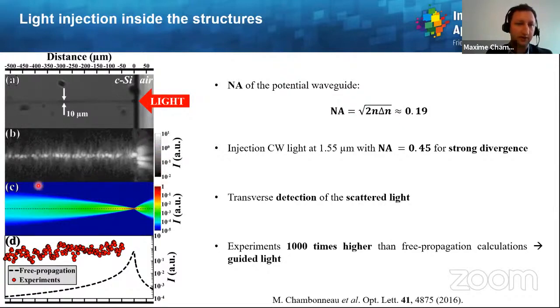And besides, we have carried out here in C and D some evaluation of the linear propagation in silicon, if one assumes that there is no guidance. So first, we can evaluate the numerical aperture of the potential waveguide, which is around 0.2. And the injection of the light with a high numerical aperture objective will allow us to have a strong divergence. So it's easier for us when we use a numerical aperture which is much higher than the one of the potential waveguide. It is much more convenient to see if light has been guided.